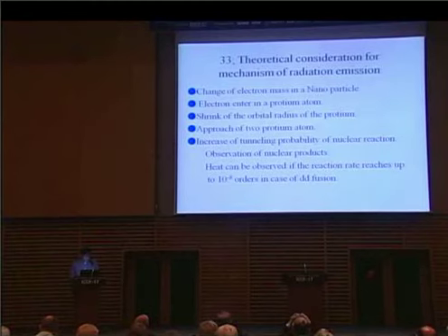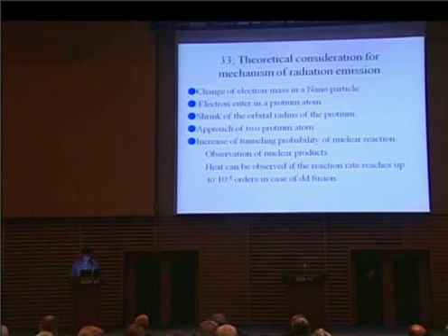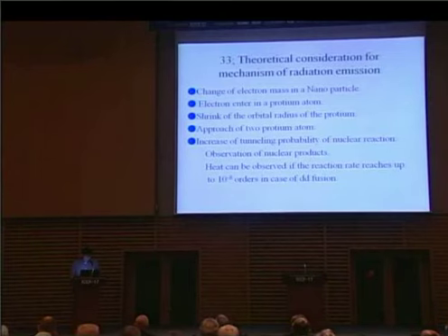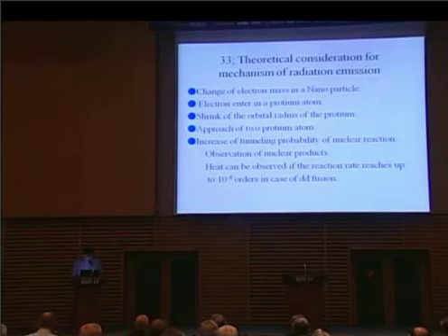These slides show the methods that were used in the theoretical analysis. We focus on the behavior of the electron in the metal particle. Several reports have pointed out that the dynamic behavior of the electron is very different in metal particles from the behavior in normal bulk. Electron is confined to a nanoband, especially in nanoparticles. This means that the electron conduction bandwidth is very limited. Such electrons will be affected by the potential of other atoms and electrons in the metal particles.